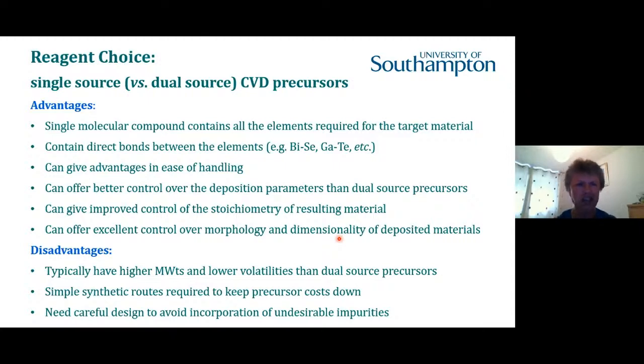It would be unfair to say that single source precursors answer all the questions. They have some disadvantages. Just to be fair, clearly by incorporating everything in a single molecule, the molecular weights are higher, and so that tends to lead to lower volatilities, which is why we are often using a low pressure process, although there are other methods, liquid injection CVD and so on, that are perfectly compatible with these sorts of precursors.